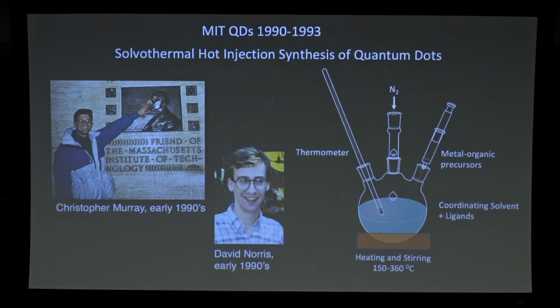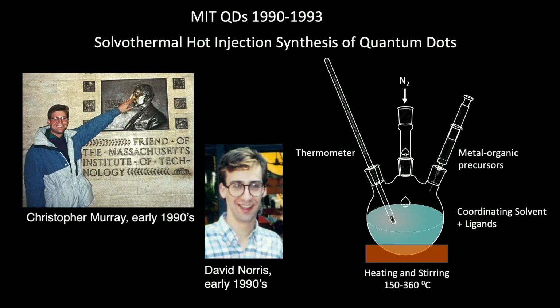Once you nucleate, then your concentration is not high enough anymore. You used up material. Nucleation stops. And the only thing you can do now is grow on top of the existing particles. That's the growth phase, and that can take a couple hours. And that slow growth then allows you to stop the reaction at any time simply by cooling the solvent and getting a very tight size distribution.